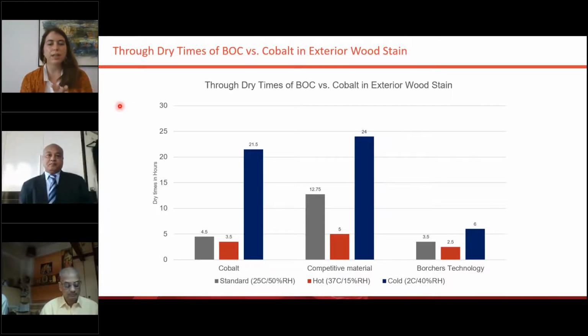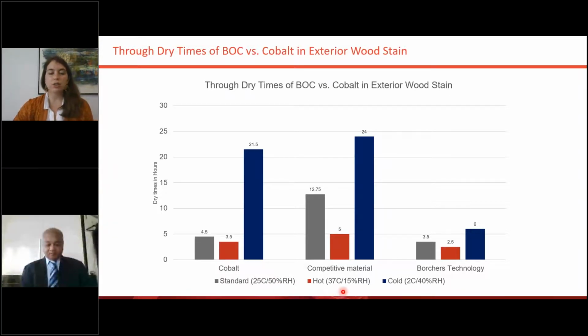So where was I? I'm talking about adverse conditions. This graph looks at dry times in hours, comparing three different conditions: standard 25°C, 50% relative humidity; hot conditions at 37°C and low relative humidity; and cold temperatures, shown in blue, at 2°C and 40% relative humidity. With this Borcher's high performance dryer technology, this accelerated ligand technology, you get low and stable dry time across all of these weathering conditions.